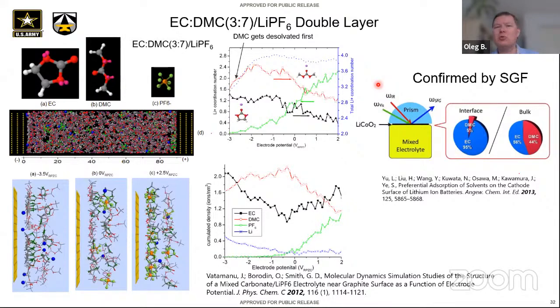That's why in previous work on Born-Oppenheimer, we did include specific LiF because, unlike pure simulations on lithium where the electrolyte gets flooded with electrons and everything, or nearly everything, gets reduced, now we have some specific surface, specifically lots of lithiums, to take fluorines from PF6, and fluorines get absorbed essentially on a lithium in LiF, creating an excess of fluorines, but they do get absorbed.